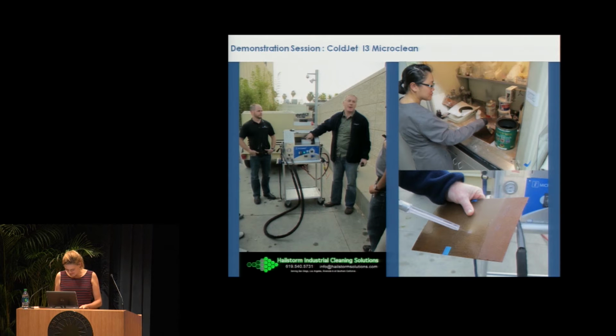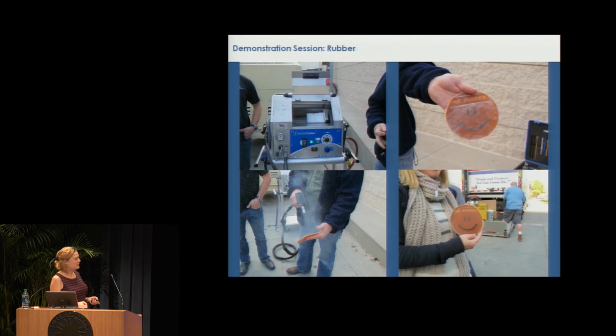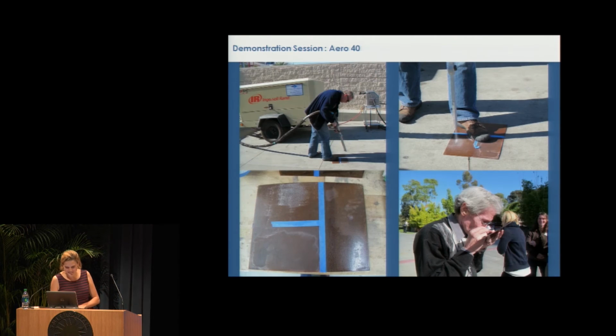But we also had a rubber project back then, and we were trying to do research on the degradation of natural rubber. And you see here our Mr. Rubber, or degraded rubber, who had a nice smiley face made with a Sharpie. We tried to blast that, and that gave really amazing results without affecting the Sharpie. But that was just a little side joke.